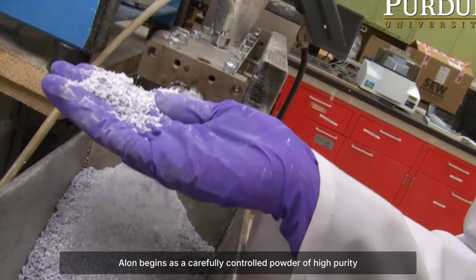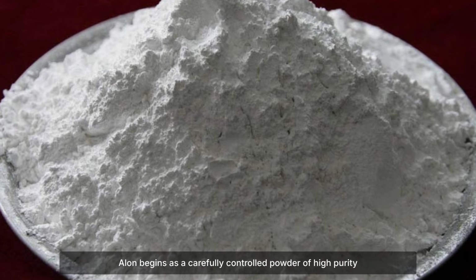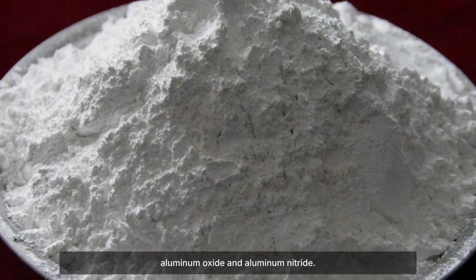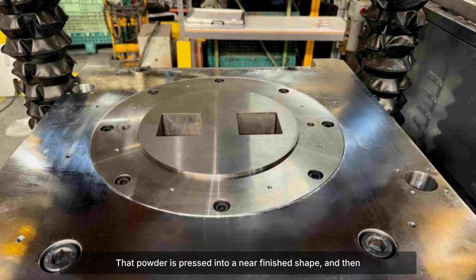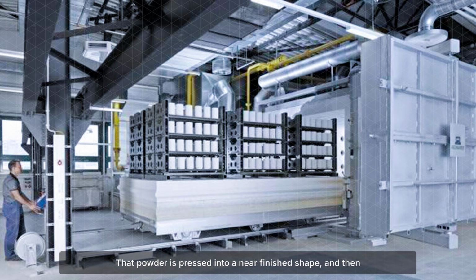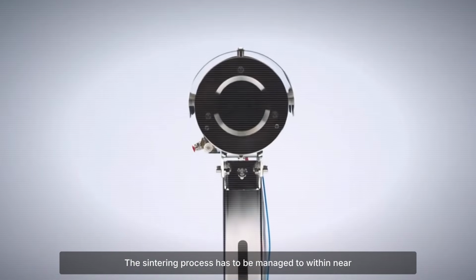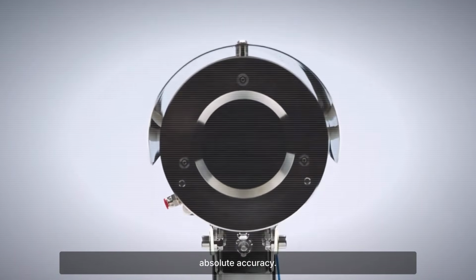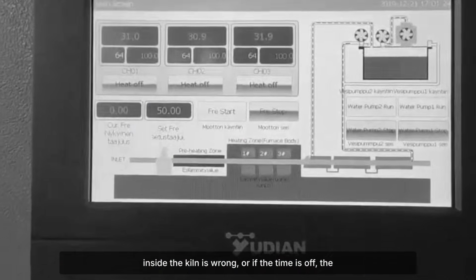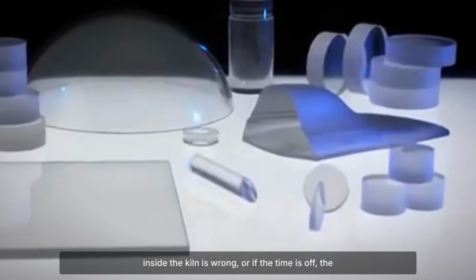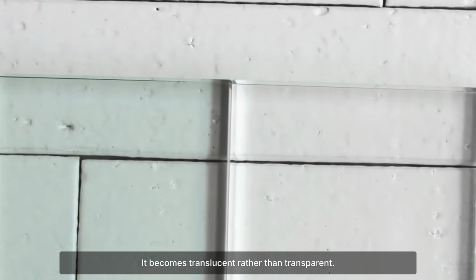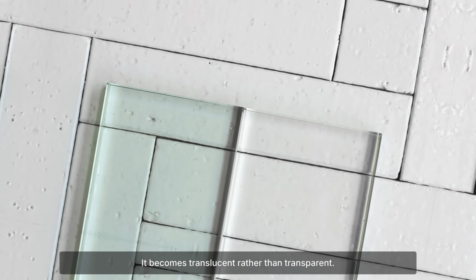Alon begins as a carefully controlled powder of high-purity aluminum oxide and aluminum nitride. That powder is pressed into a near finished shape and then sintered, meaning fired in a kiln at extreme temperatures for days under precisely controlled conditions. The sintering process has to be managed to near absolute accuracy. If the temperature profile deviates, if the atmosphere inside the kiln is wrong, or if the time is off, the material does not achieve optical clarity. It becomes translucent rather than transparent.